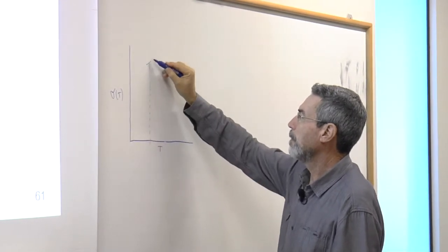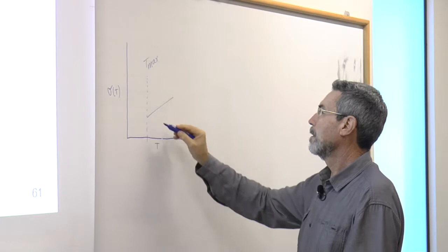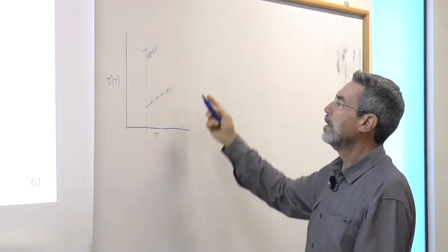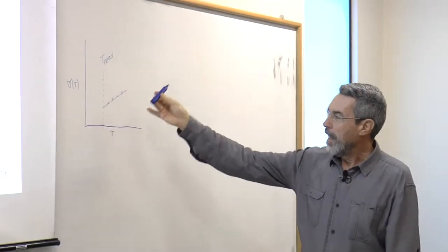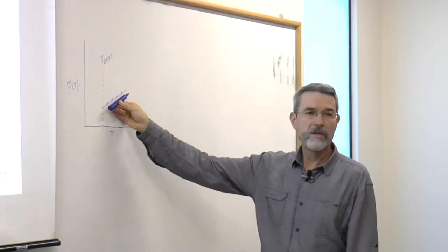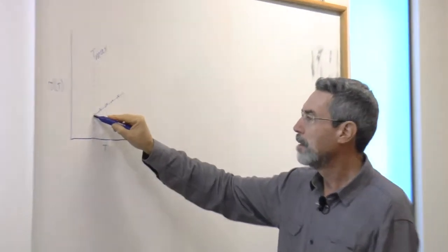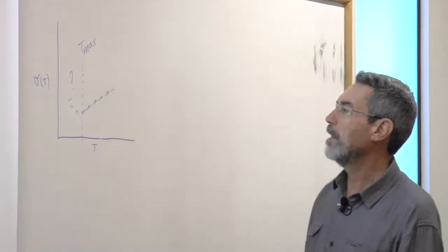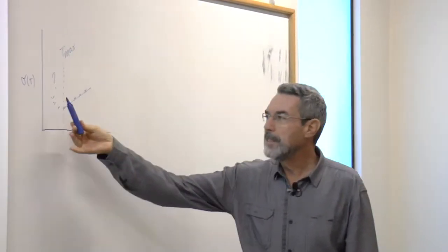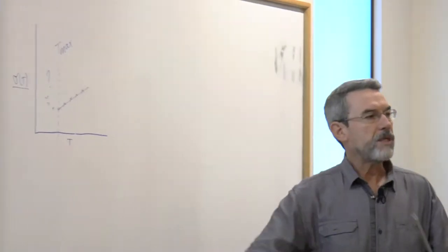this is the temperature of maximum steady state nucleation rates, we see that the values of surface energy to restore agreement have to increase slightly with temperature. The derivative here is very small, but it's positive, so it increases with temperature. But here, below the maximum, it has a very strange behavior. This is the strange behavior of the surface energy that comes out from force-fitting experiment and theory to agree.